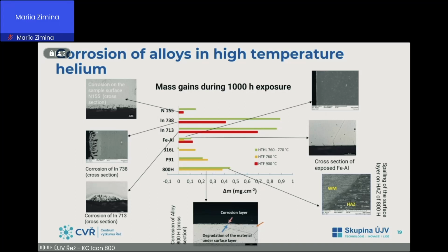So this slide summarizes the results of testing the materials. Very good corrosion resistance was shown by austenitic steels even at higher temperature, but the mechanical properties of these alloys are not good at such high temperature. Also very good corrosion resistance was shown by iron and aluminum alloys. Local corrosion going relatively deep into the material was observed on cast Inconel alloys.